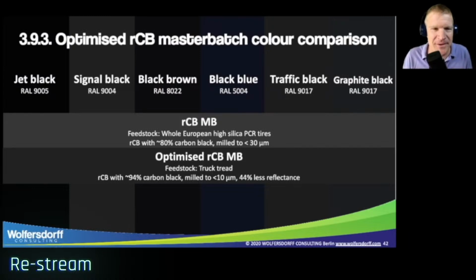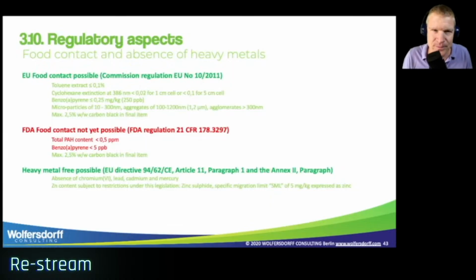However, if we compare it on the left-hand side to the jet black, we can see that still it is gray. It is a dark gray, but it is gray rather than black. But you can see also there's a net improvement over the standard high silica passenger car tire recovered carbon black. So I think this is a very nice result. I think this can be further tweaked, but just to show you a nice improvement.